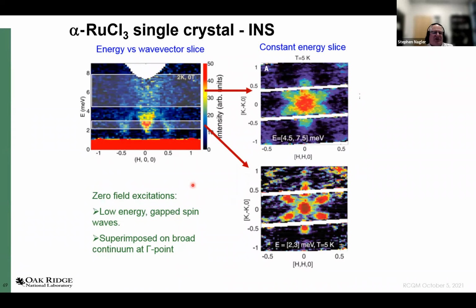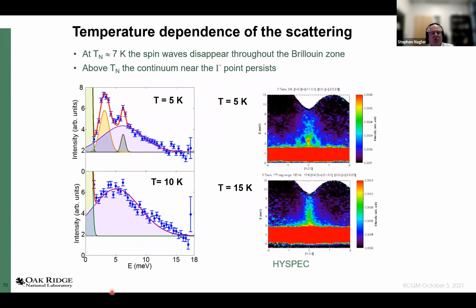And if I do this as a function of energy, and I look at the intensity at one momentum, which corresponds to the gamma point, what I see at low temperatures is a sort of broad piece with some sharp peaks.